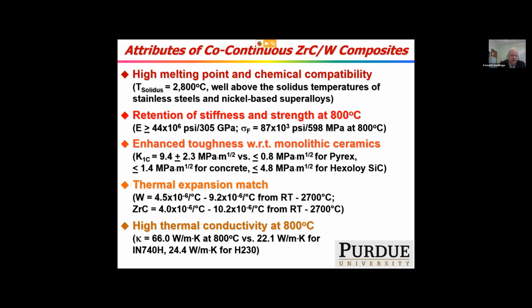But it's also tougher than monolithic ceramics. As I mentioned, tungsten at elevated temperatures provides ductility. The toughness of the cermet, in fact, has been measured to be about 9.4 MPa root meters. To put that in perspective, that's more than about 0.8 for relatively tough Pyrex glass, 1.4 for concrete, and about 5 for silicon carbide. In fact, we've done a poor man's toughness test, we can drop these things from a meter and they just bounce basically. So they're really quite tough cermets.